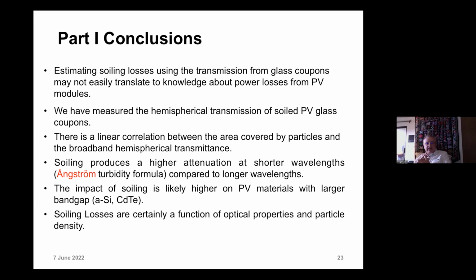So some of my other colleagues are looking at the optical properties of, say, soot or sand from the desert, and they're making plots of the transmission as a function of wavelength, which might be characteristic for their region. For instance, in Egypt or Qatar or in Morocco, you might find different times of the year have a different transmission versus wavelength. And then you can say, oh, those particles, they seem to be more sand or calcite or soot or wood particles. And so this allows us to do a little bit of very easy spectroscopy to perhaps start to characterize soiling in different locations.